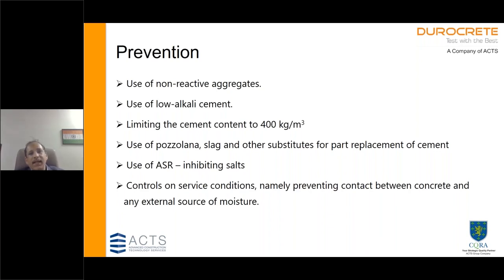And another way is that, since the reaction requires moisture, you can control this by protecting the subsurface concrete by various films, membranes that are available, to prevent the moisture ingress.